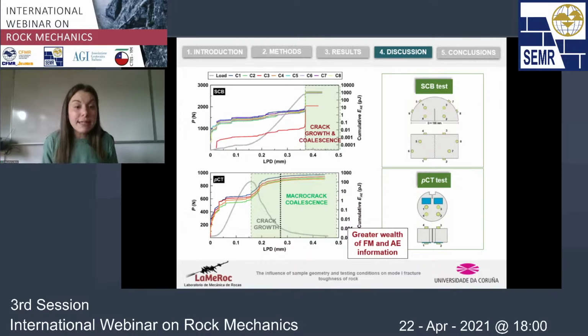However, in the case of the PCT, we observed that although there is energy released before the peak load, the major part of the energy is released here after this moment, and the energy is not released as suddenly as in the case of the SCB. In this case, thanks to having this control on the post-peak, we can assess the energy needed for crack growth and macro crack coalescence. So the PCT is giving us a greater wealth not only of fracture mechanics information, but also of acoustic emission information.